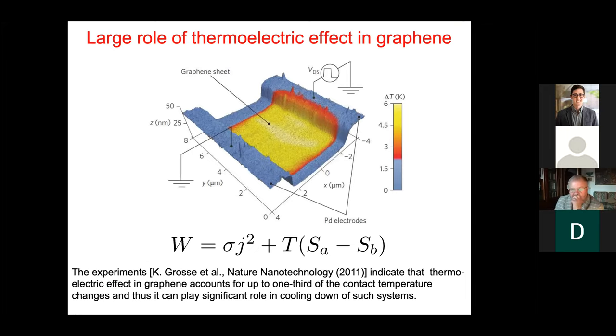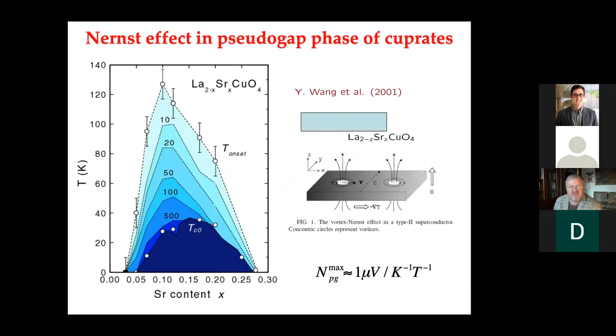Then, the large role of the thermoelectric effect in graphene. If we assume to use graphene in some nano devices, it is necessary to be very attentive because of the large value of the Seebeck coefficient, and up to 30% of heat can be released at the contacts. Then 20 years ago, the huge Nernst effect, so Seebeck in Hall effect, in thermal Hall effect, was found in high temperature superconductors.